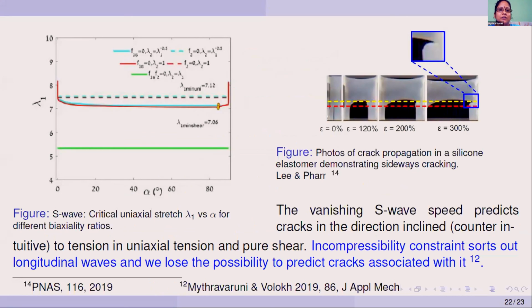That is, in the case of uniaxial tension and shear, the critical value of stretch lambda 1 occurs when alpha is around 82 degrees, which is to say that the crack localizes in an inclined direction. So this is counterintuitive, as we would expect cracks to localize in a direction perpendicular to the applied stress. So it should be emphasized that imposing incompressibility constraints sorts out the longitudinal waves, and we lose the possibility to predict the cracks associated with these longitudinal pressure waves. With this, I would like to conclude my presentation.